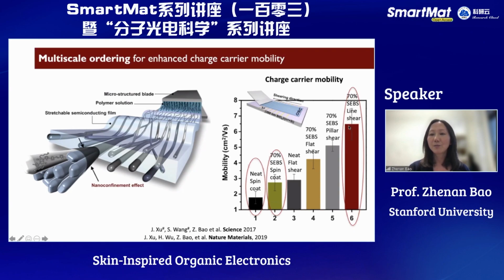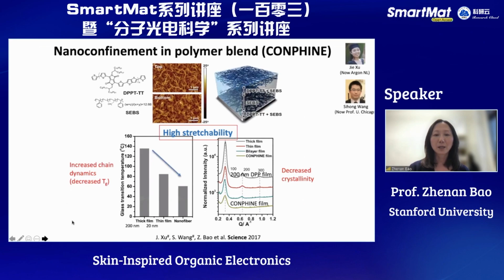And then we can further boost the mobility if we control the coating so that there's some alignment of this nanostructure. Then this mobility can be even several times higher compared to the best possible for this neat polymer. And this also at the same time allows us to include stretchability in these materials. So we're essentially adding a new functionality without compromising, but rather enhancing the charge transport, which was completely unexpected.